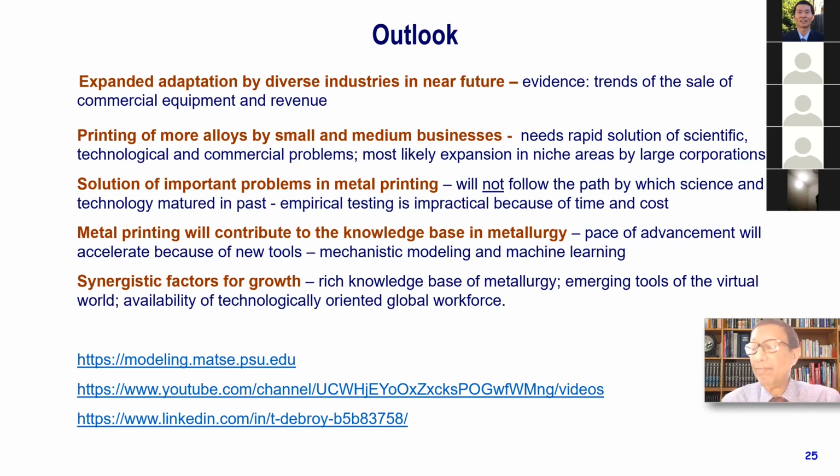The next question will be whether laser wire additive manufacturing will dominate laser powder bed fusion. Laser is more expensive than electric arc. So I think the overwhelming majority of wire feed is where the primary motivation is to expedite production. You're not making layers like 30 micrometer thick. You are making layers that are maybe 1 millimeter thick. And you can do that much more inexpensively using a gas metal arc power source.